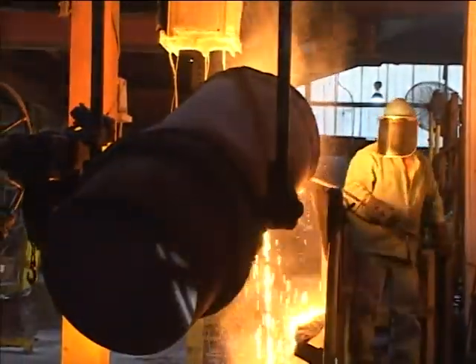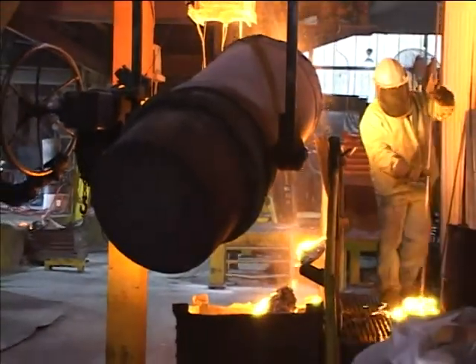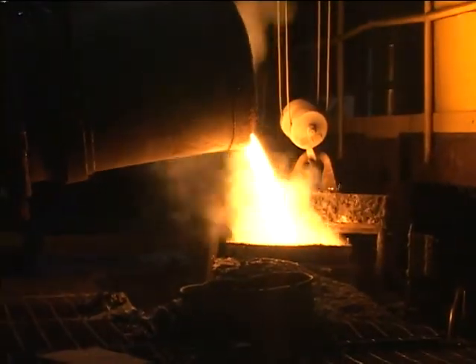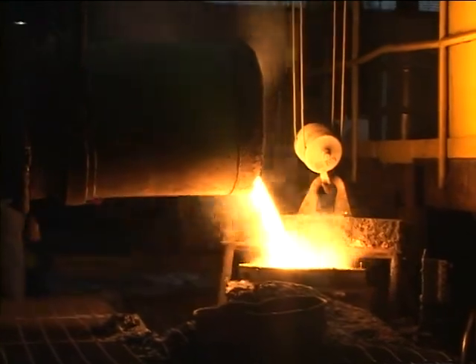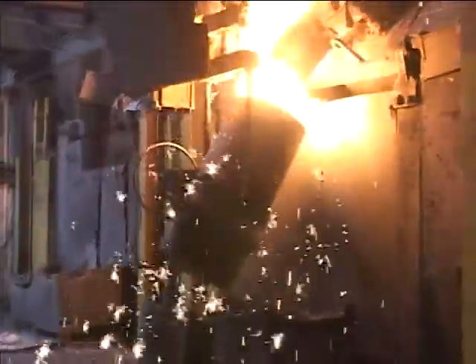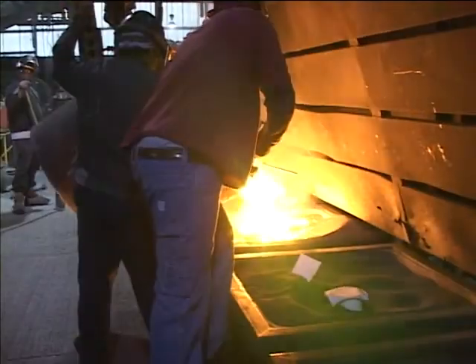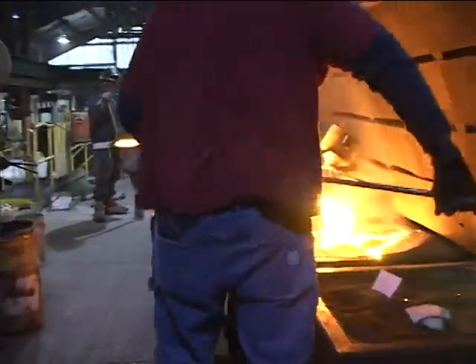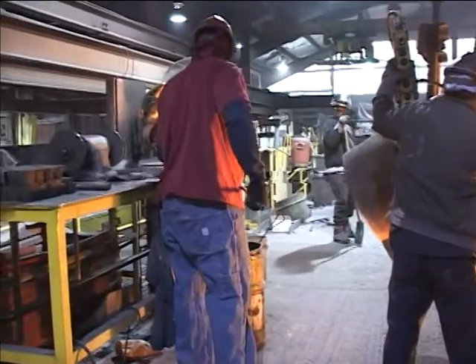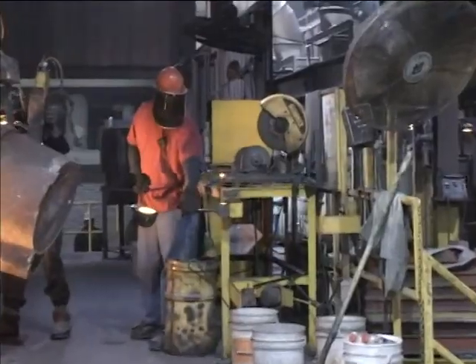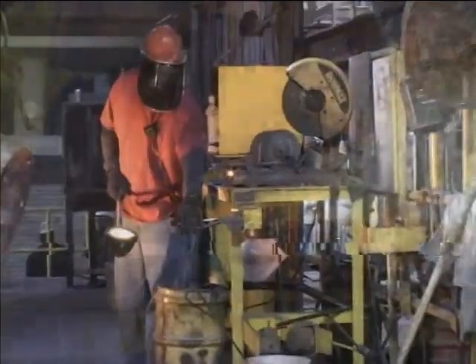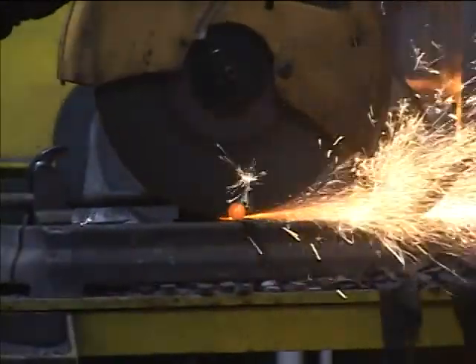To ensure the highest metallurgical quality, process controls begin with the purchasing of raw materials and continue through the melting and alloying phases where Citation manipulates the base chemistry to create various grades of ductile or gray iron. Multiple chemistry checks and a double nodularity confirmation, both on the pouring deck and minutes later in the lab, ensure the microstructure is of the highest quality ductile iron.